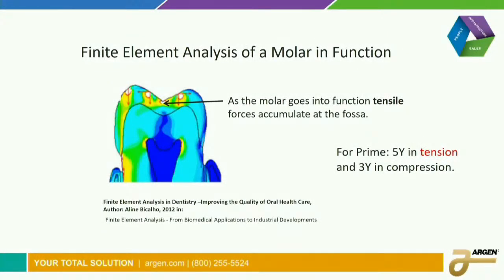And when you do the computer work on that, sure enough, here you see the stress goes in opposite directions. That means this is in tension. So before we saw that bridge actually had the occlusal surface in compression, and we thought that was good because that's where our 3Y was in the case of the Ivoclar material. But in fact, on the molars, you don't have that situation. On molars, even though it's a single unit, when that goes into function, because of the occlusal fossa, you're going to have a tensile force in that area. So again, we see fractures on molars a little greater on some of those multi-layer ones.